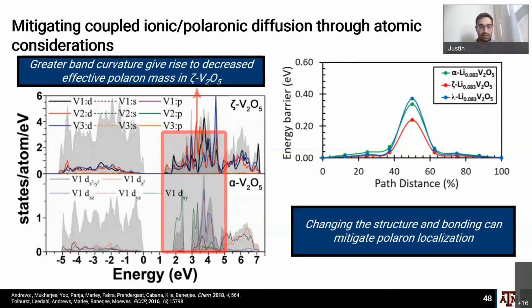So the first thing, and this was done in collaboration with Alex Moses' group at University of Saskatchewan. What we were able to show is that as we change the structure from a 2-dimensional structure, alpha V2O5, to a 1-dimensional structure, one interesting change is that there are more crystallographically unique vanadium sites, and what that does is give rise to a more dispersed density of states within the conduction band.